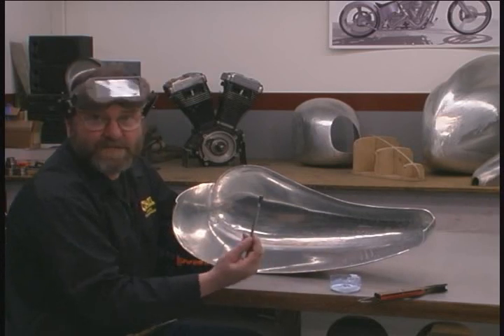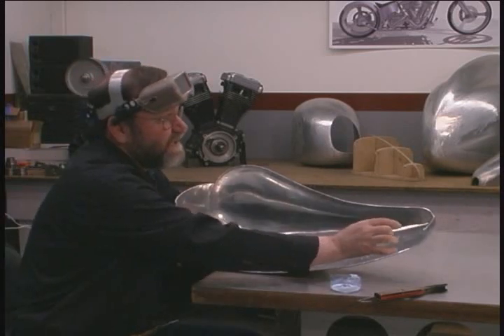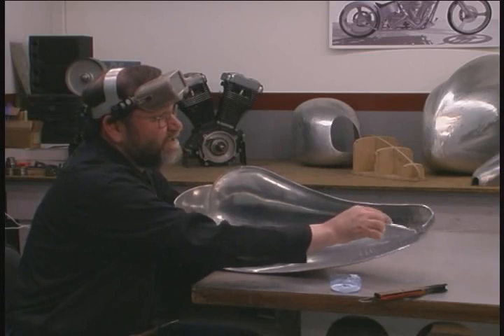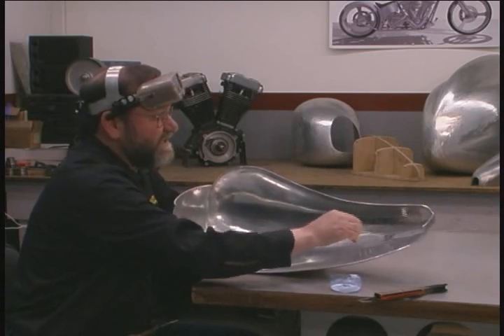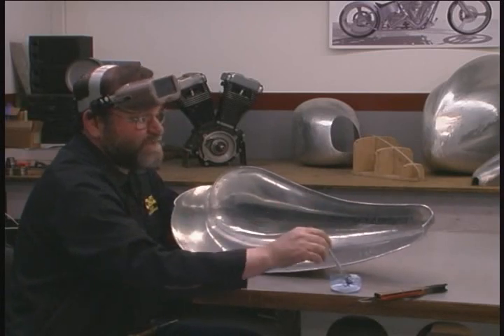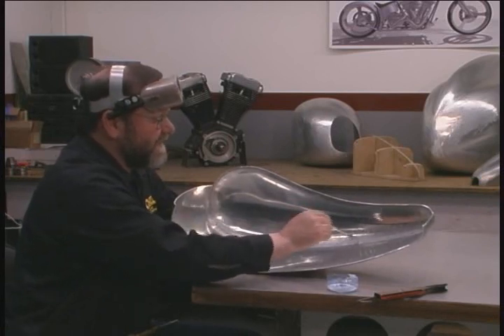You need to use a special flux. This is aluminum welding flux, and it comes as a powder which you mix with water to make a light paste. And then that paste is brushed onto the joint, both on the inside and out.